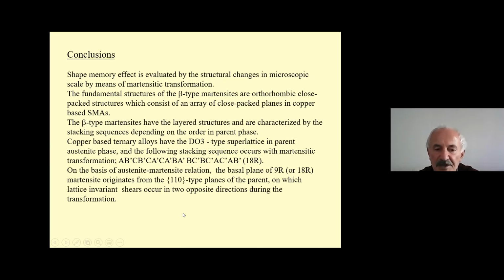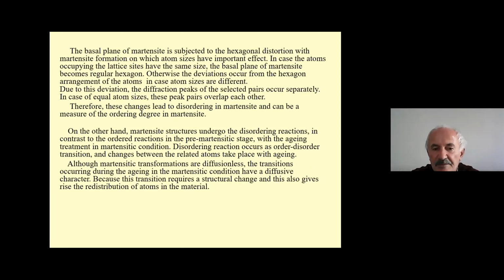On the basis of the austenite-martensite relation, the basal plane of 9R or 18R martensite originated from the {110}-type planes of the parent phase, on which lattice invariant shear occurs in two opposite directions with the martensitic transformation.